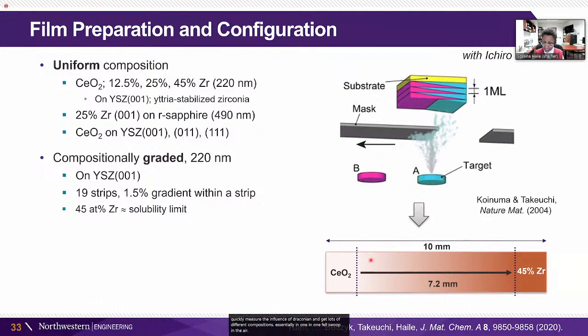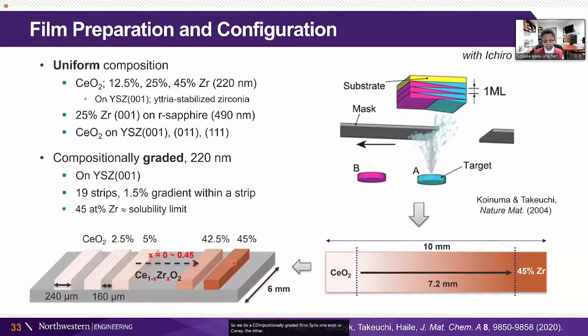In the era of big data, this is becoming more and more important. So we do a compositionally graded film, ceria at one end, zirconia at the other end, and then we pattern it so that we know where we are when we do the XANES measurement across here. We got 19 strips, but given time on the synchrotron, we only measured maybe about 9 or 10 of them.